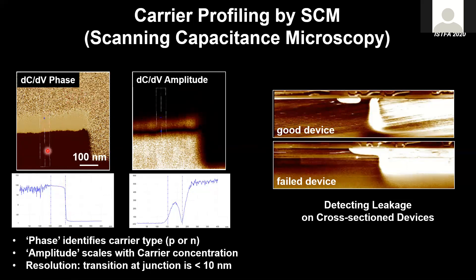The amplitude image relates to carrier intensity or dopant intensity. We can make sections through these images to get more information on the specific carrier profile in the direction of choice. A typical failure analysis example is to quickly cross-section the device and look for the presence or absence of implants — or, as in this particular example, to look for a short between two doped areas. In this failed device, these two doped areas are clearly shorted out, relatively easily detected by these modes.